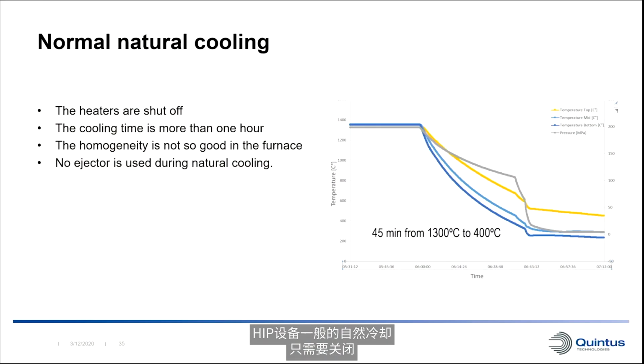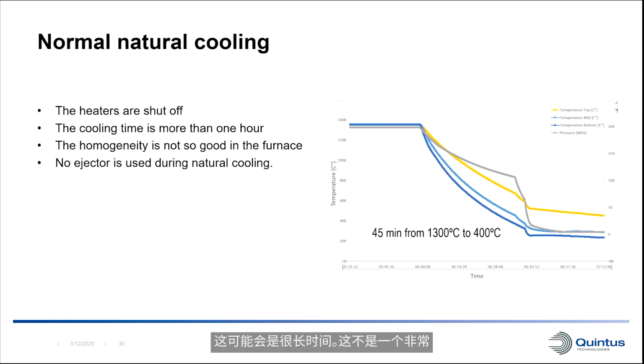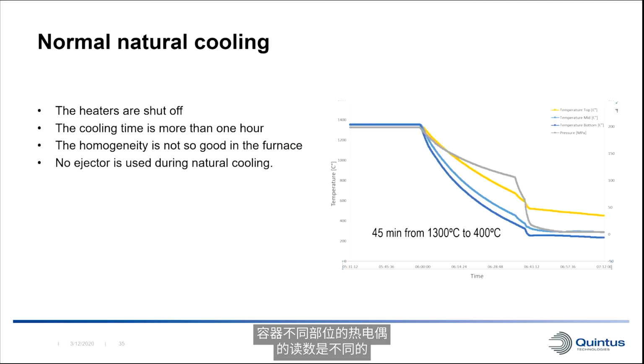Normal natural cooling of HIP equipment entails shutting off heaters, and the cooling time is dependent on the amount of cooling of the actual vessel itself. And this can be very, very long. It's not a very homogeneous cooling either. We can see that the thermocouples in different parts of the vessel give very different readings in this particular graph. So here you can see a 45-minute cooling from 1300 C to 400 C. And the ejectors are not used in this normal natural cooling to assist.